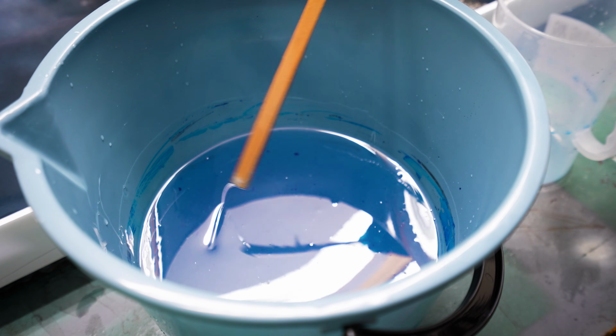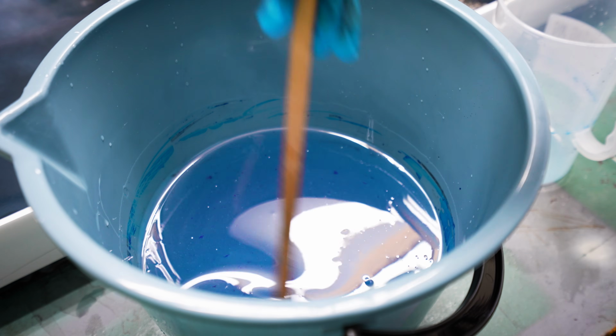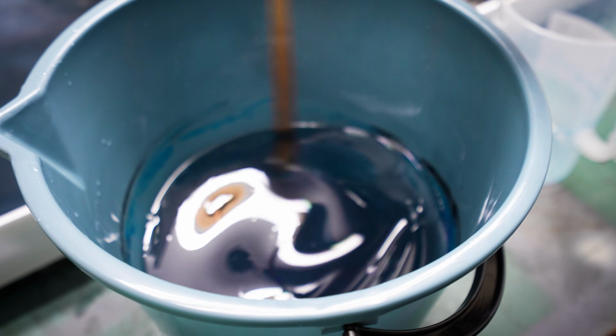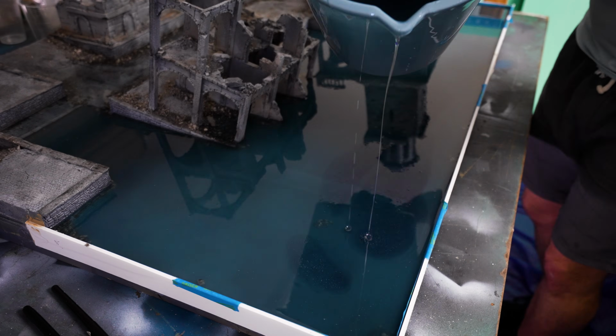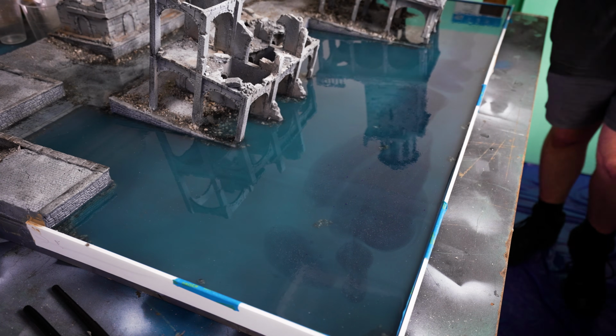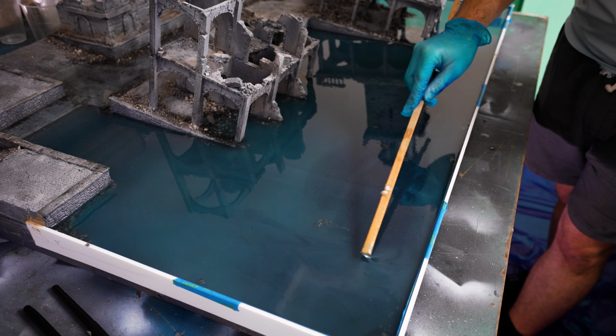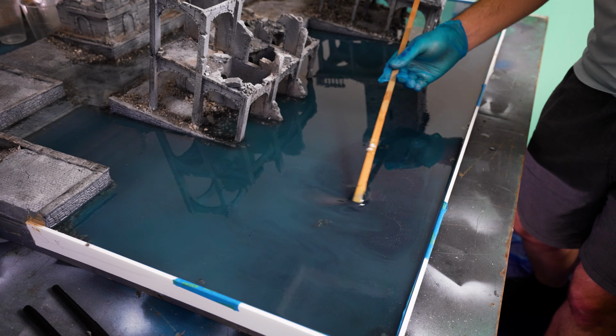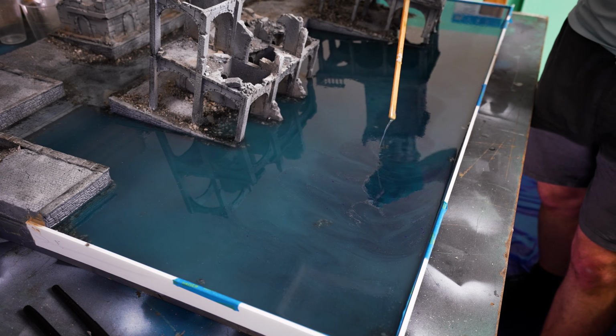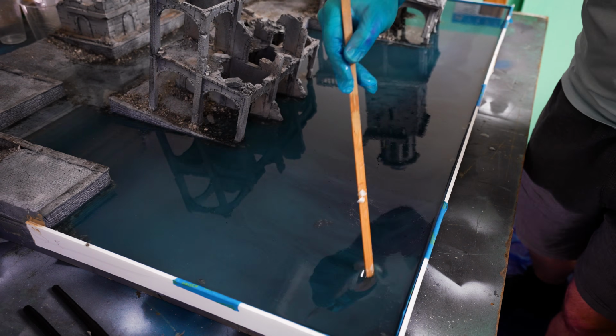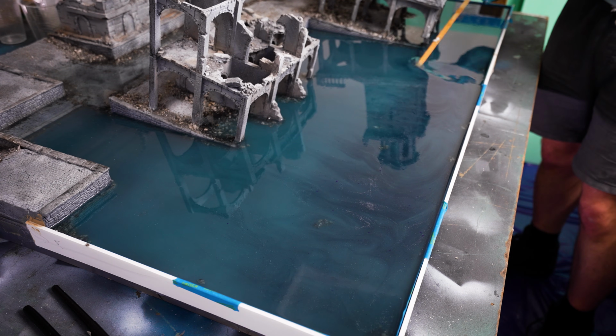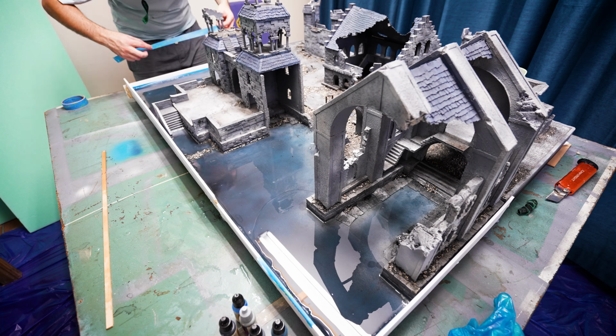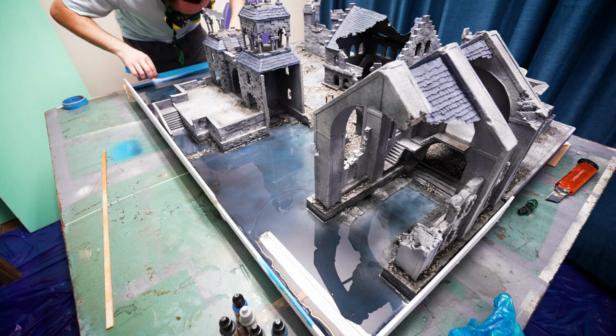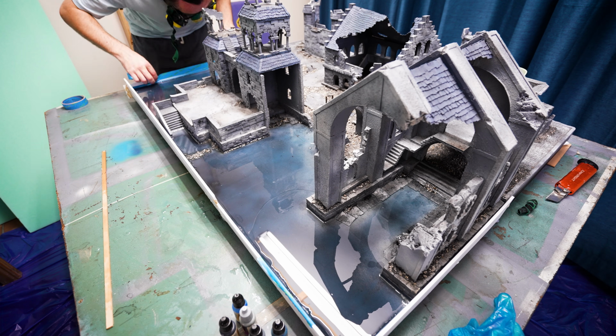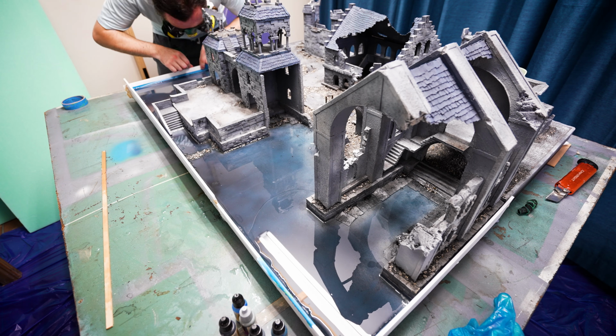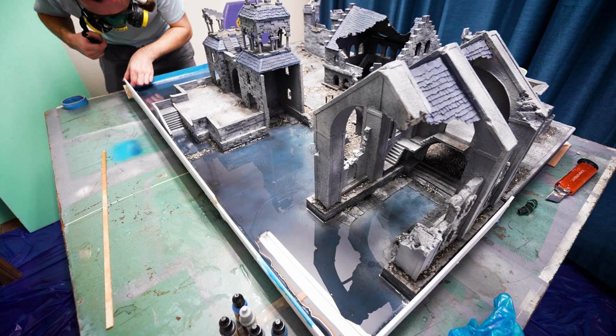and all of that blue paint just became dry, large particles blasted through the resin, and they just would not dissolve no matter how much I mixed it in. Not wanting to throw out 3 kilos of resin, I just poured it in anyway, and it was much darker and required a lot of massaging to blend into the mid-tone, but over time it ended up looking really good, but the little bright blue flecks of paint were everywhere. Over the rest of the day, I was constantly fishing them out when I saw really large ones, and all the small ones will hopefully not get noticed under future layers of resin.